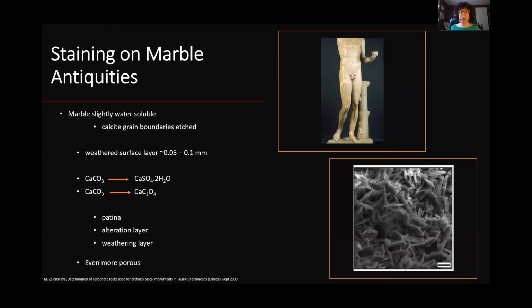Marble is unfortunately slightly water soluble, and when it's exposed to acidic groundwater or acidic cleaning solutions, then the grain boundaries of the calcium carbonate crystals start to get etched away, and it becomes even more susceptible to staining. And it also develops a weathered surface layer. And you might think 0.1 millimeter, that's tiny, but in fact, that's going to be extremely visible. Very, very thin layers can enact dramatic changes to the surface of an object.